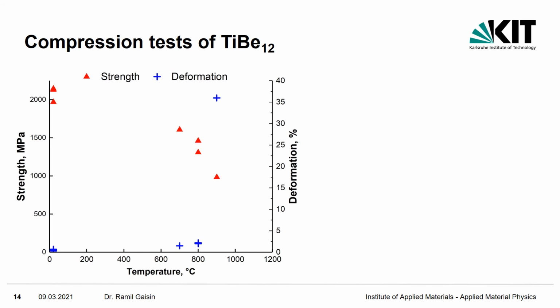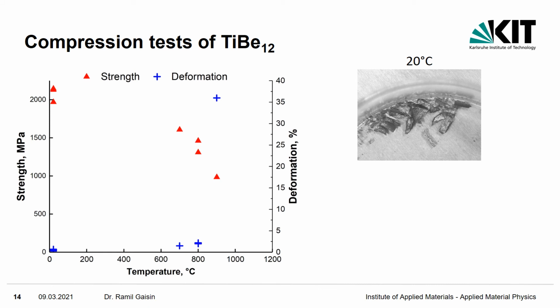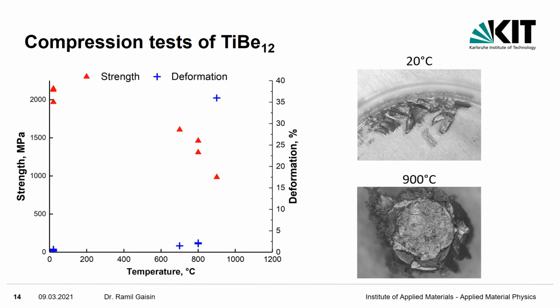Compression tests of beryllides were carried out at room and elevated temperatures. Taking into account its low density, the material shows a very high compressive strength of about 2000 megapascal at room temperature and about 1000 megapascal at 900 degrees. The material is brittle up to at least 900 degrees, at which the beryllide deformed plastically. The experiment is still ongoing and not yet completed.